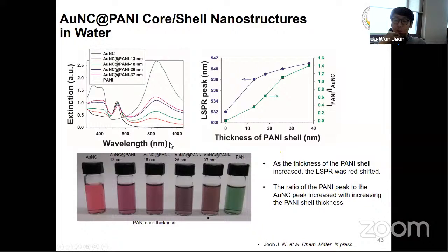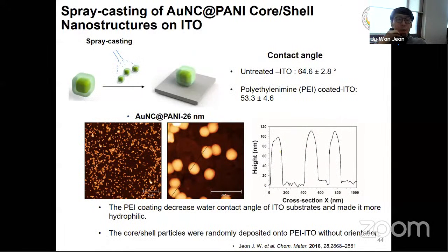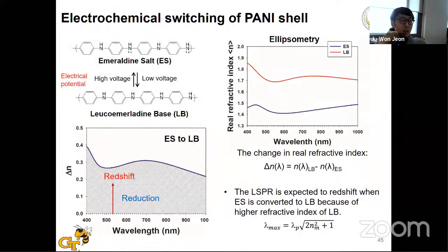So this is the UV-vis spectrum, and now the color is different because of the existence of the shell. And then we coat the conductive ITO substrate with the polyaniline core/shell nanostructures using the 26 nanometer shell. And then we can find some of the monomer and dimer, and the height profile was also characterized. And then when we apply the electrical potential, we can expect the reaction between leucoemeraldine base and emeraldine salt.